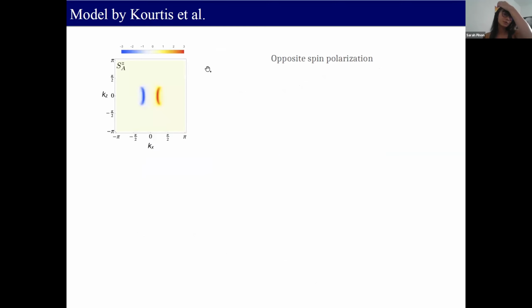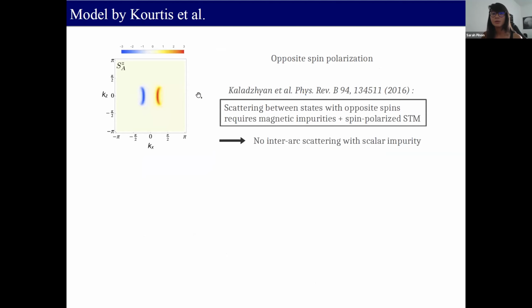One thing we did when looking at this system was to look at the spin polarization of the Fermi arcs. And we saw that the Fermi arcs have opposite spin polarization. This is important because in one of our previous papers, we showed that scattering between states that have opposite spins can only occur if we have magnetic impurities, and then they can only be seen in experiments if we have spin polarized STM. So in our case, we expect that there will be no inter-arc scattering if we have a scalar impurity, and this is what is considered in particular by Kourtis et al. in their paper.